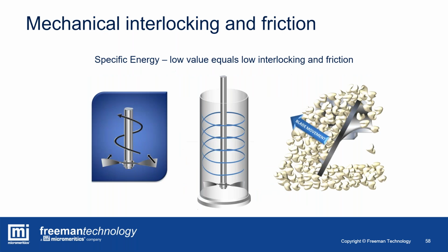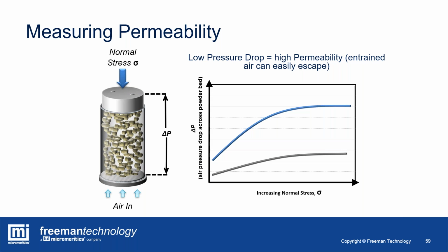We measure with our unconfined flow, or the specific energy test, the upward measurement, and so this is the resistance of the powder bed to being lifted and to flowing just under gravity. It's very good at looking at the effects of interlocking and friction. And then we use the permeability configuration to measure the pressure drop through the bed, so imposing a consolidation stress on the x-axis, a gas velocity which you can set to any desired amount or go through a range, and we measure, whilst confining that powder bed under a consolidation stress, the air pressure across that powder bed. So a powder that's got low permeability would mean you would have a high air pressure differential across the base or across the bed, because it's difficult for that air to percolate through the particles, between the particles, and out into the atmospheric relative pressure.